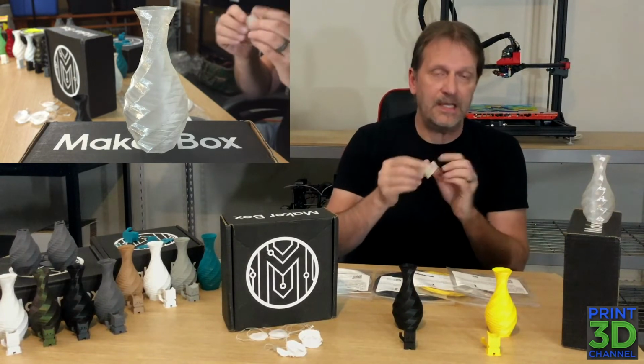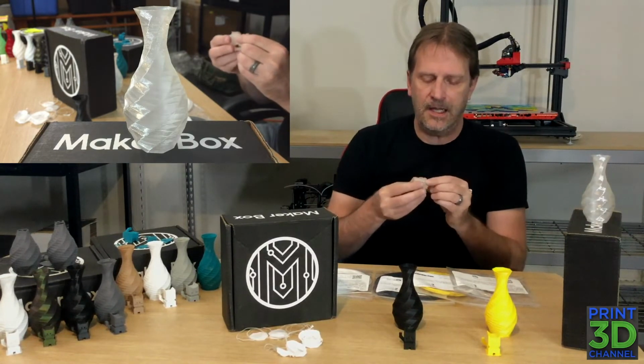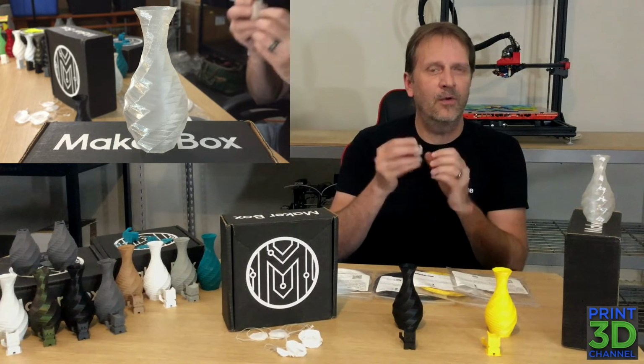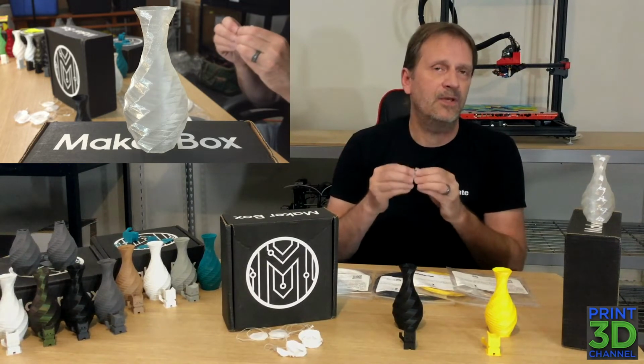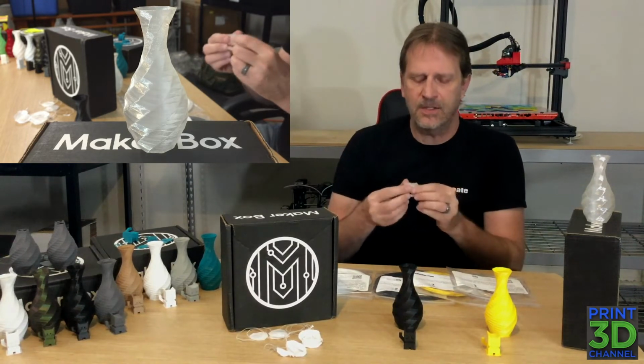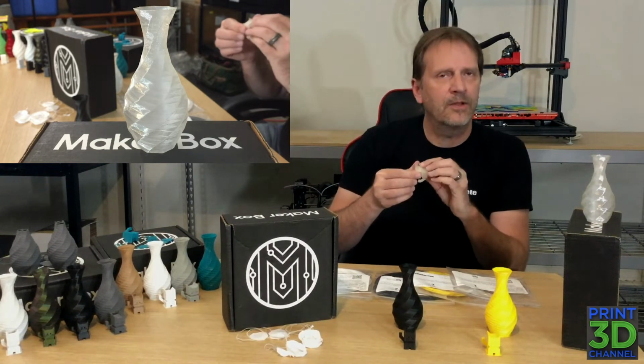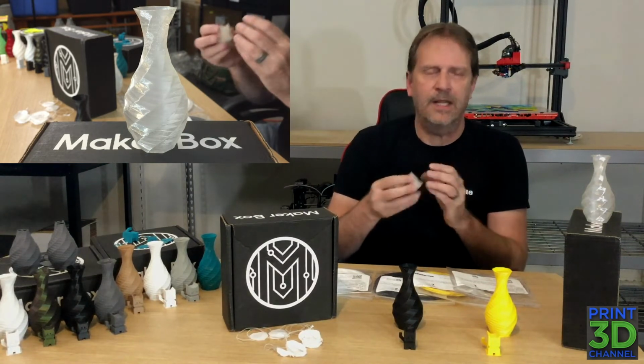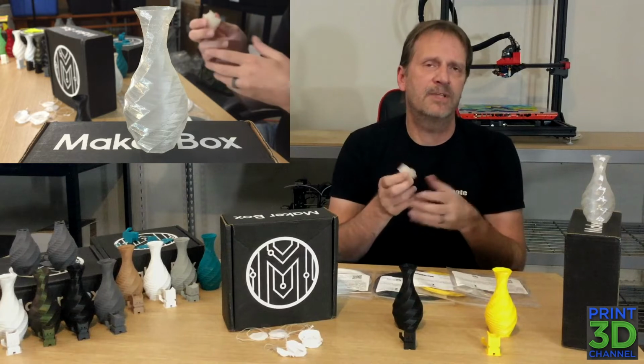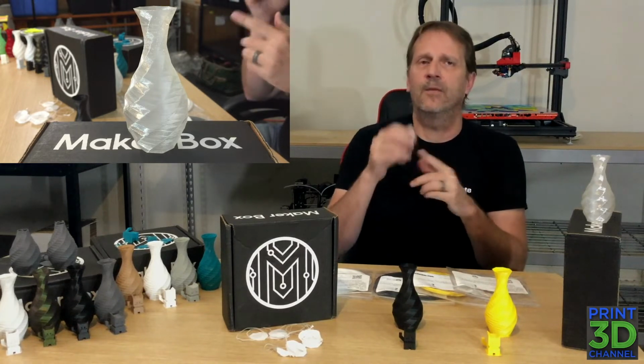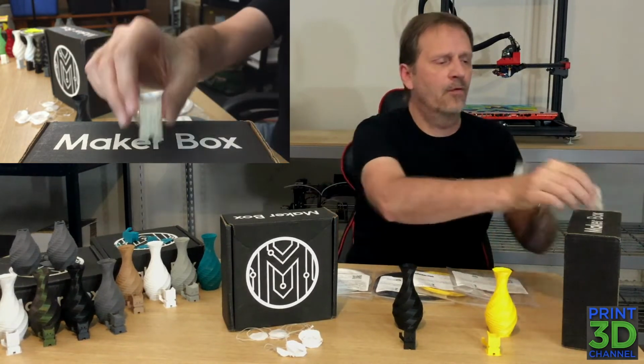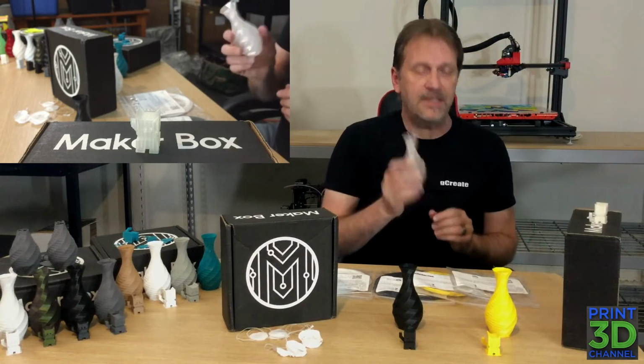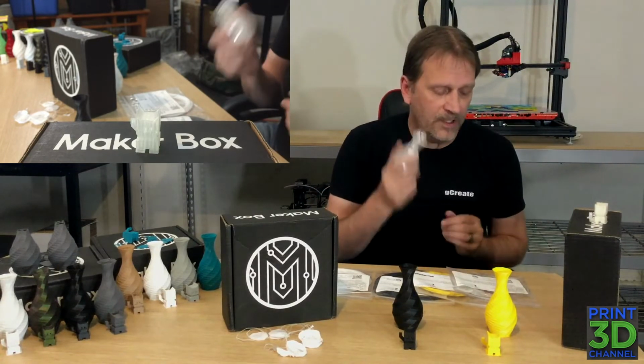But 240 C on the hot end, and I wanted to lower the temperature, but I know there's layer adhesion issues with TPU if you don't keep the temperatures high. So it does have a little bit of that curling, a little bit of corner melting aspect to it, but it's nominal. And if I was printing some other objects, I definitely would pay attention to that with some other print adjustment. But overall, I think this TPU from IC3D printed awesome and really had no problems with it.